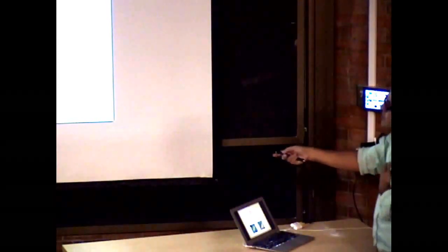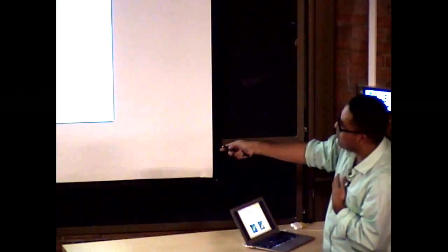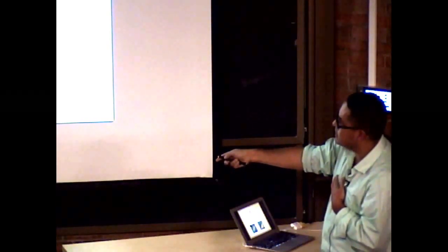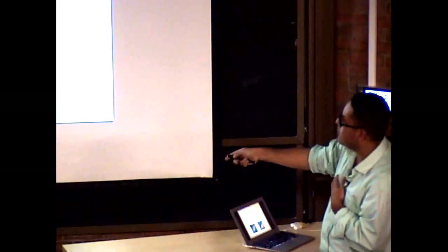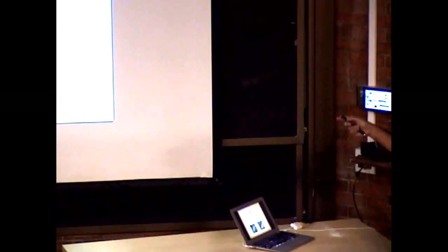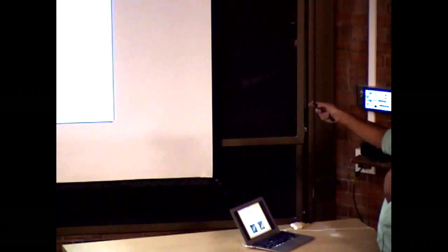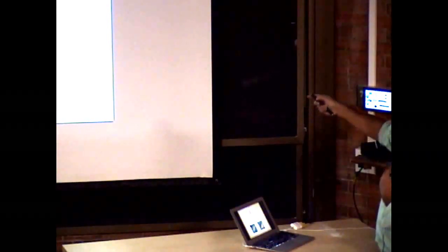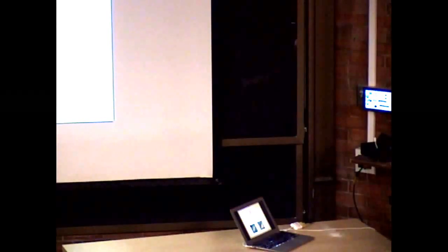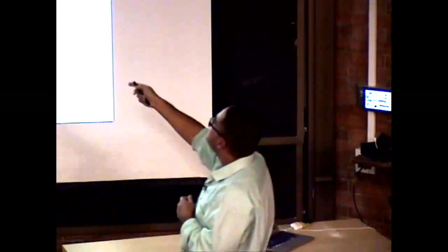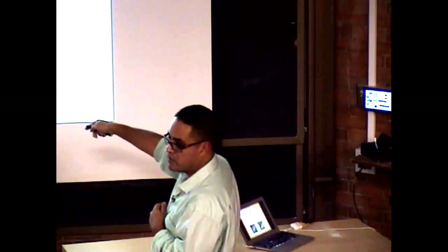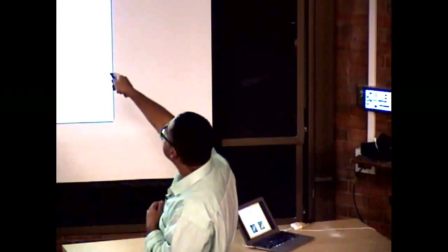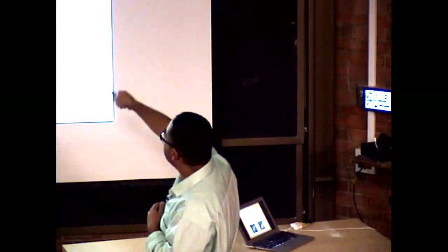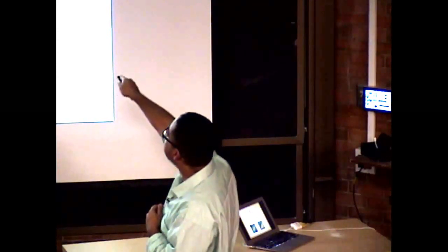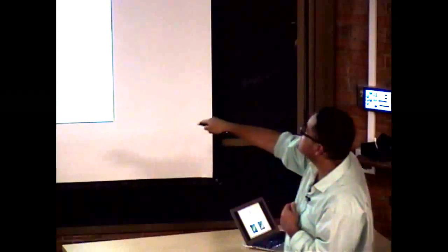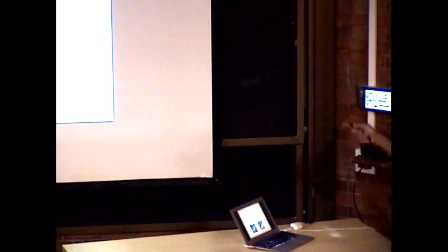But the main point is that we have a signal that's very broad along this diagonal, very narrow along this anti-diagonal, real and imaginary. This is just to drive the point that this is a pump axis, a probe axis at a particular pump-probe time. What is I? This is the signal, the intensity of this signal. This is the signal that we measure that is a function of the pump spectral axis, the probe spectral axis, and a pump-probe delay.